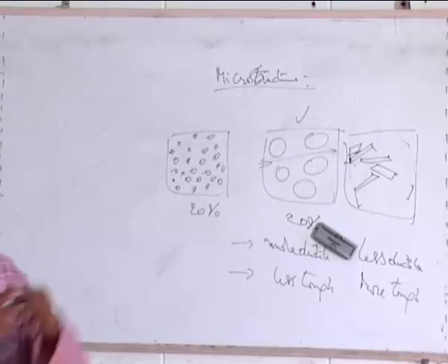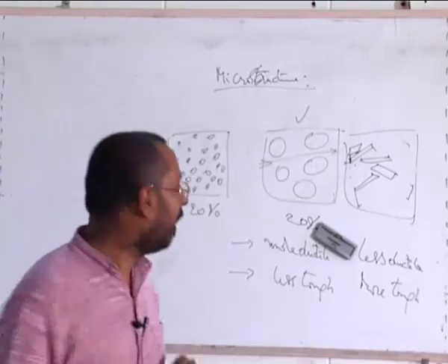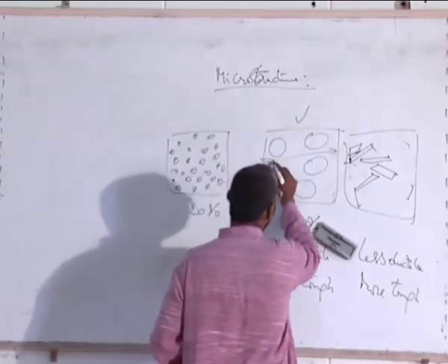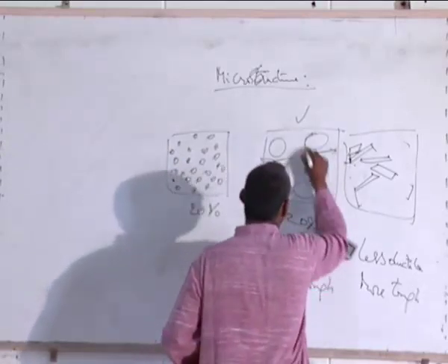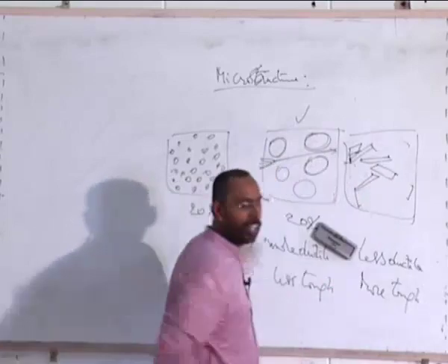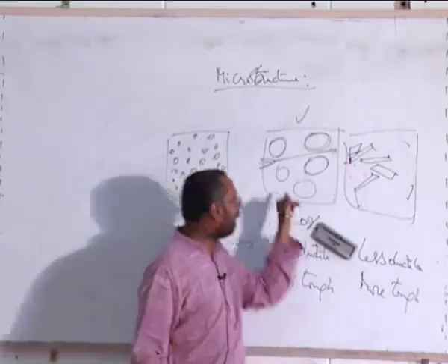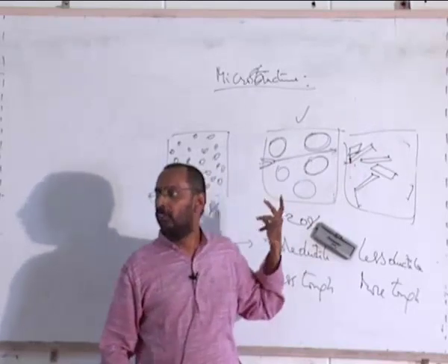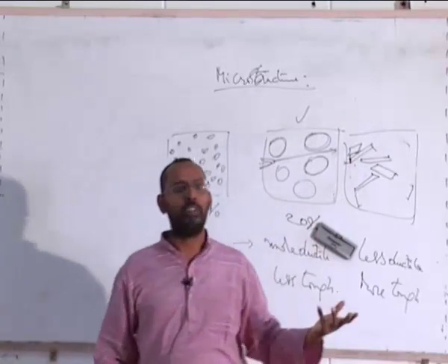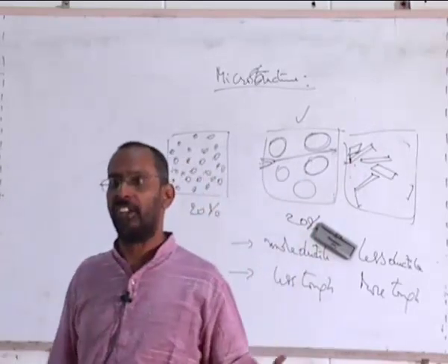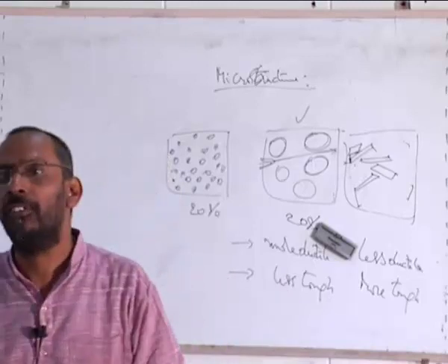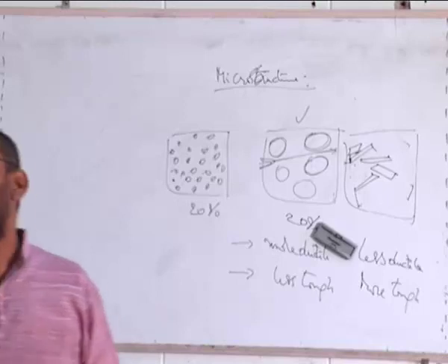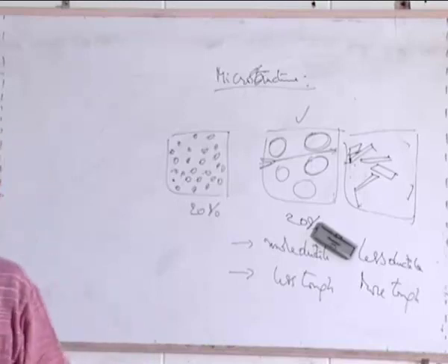The cracks get diverted very easily, and as a result you will see. Whereas here, the moment a crack is initiated, the circular spherical particles do not offer anything, it simply goes. And here the crack nucleation is more difficult because there are no sharp edges. Because there are no sharp edges, there is no triaxial state of stress, there is no stress concentration, so crack nucleation is difficult.